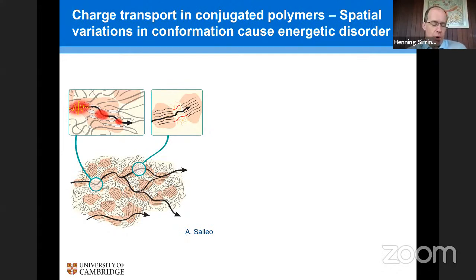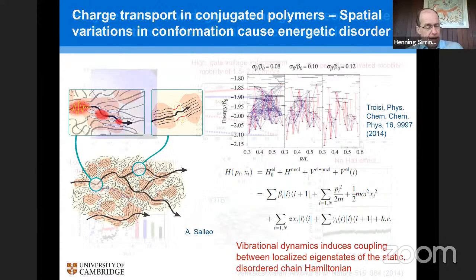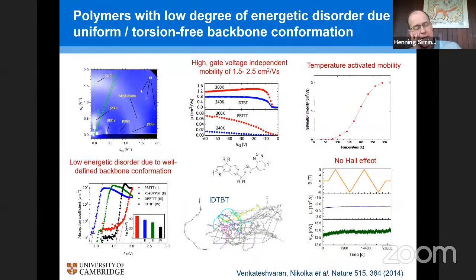And this broadening of the density of states due to structural disorder used to dominate the charge transport physics of organic systems. But in the last few years, there's been a lot of progress, as I mentioned, and our group, as well as other groups, have discovered polymeric systems where this energetic disorder is quite small. The main reason for that is that we've been able to make systems that have very well-defined chain conformations. So this is an example here of a system that we call IDTBT. It's this polymeric system here.